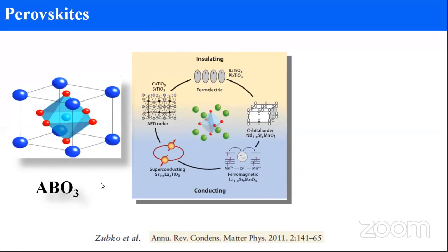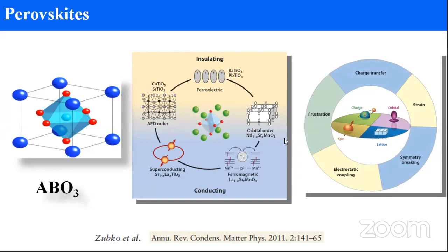You dope a little bit of lanthanum, that will show superconducting property. And this one is a small octahedral rotation. This octahedral rotation will create antiferrodistortive order, which strontium titanate and calcium titanate are some of the examples of. Okay, and also in this class of material, you can have the charge ordering, or spin ordering,